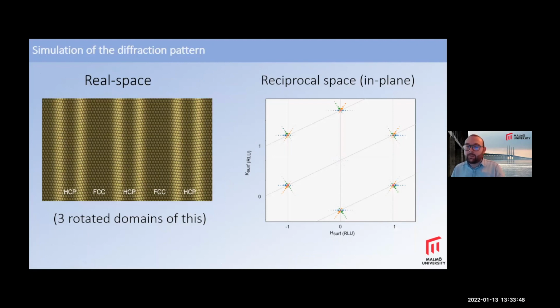And if we simulate what a reciprocal space pattern should look like, so we have a real space model like this, and we have three rotated domains of this, we get a pattern that looks like this. So at the integer reciprocal space positions, you have your CTRs, and then surrounding them, you have these extra spots which are due to the surface reconstruction. So the different colors represent the different rotational domains.